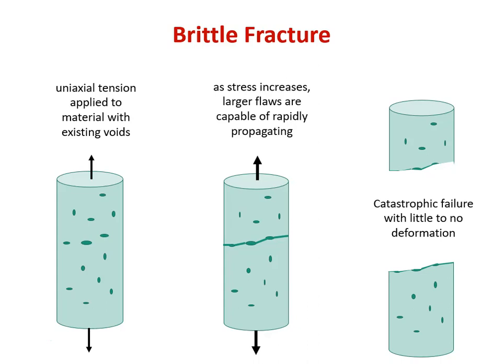the void space. So we're gonna put this in our Instron, and we're gonna start loading it up in uniaxial tension, and it's gonna extend a little bit elastically according to Hooke's law with our Young's modulus related to our strain. And as the stress increases, we're eventually going to get to the point where one of those big flaws reaches the threshold for propagating. And you can see we now have, looking at those larger ovals kind of a third of the way down, without any other plastic deformation in the sample, those just literally took off, joined, and propagated all the way across the sample. And now it's literally in two parts, the load drops, and